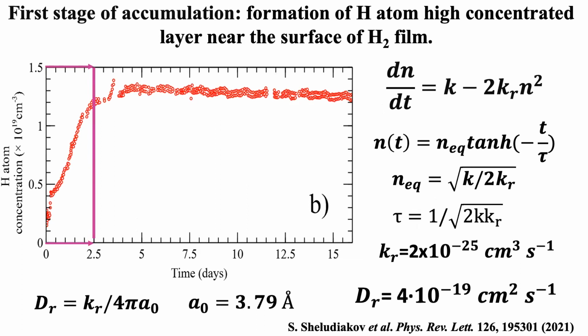So we can find this solution, and we know this equilibrium concentration from experiment. We can determine the rate of accumulation from the slope of this curve. In this case, we can calculate the rate due to recombination of the atoms, and this rate from this particular experiment was found to be this value. According to this equation, we can find the diffusion coefficient due to recombination, which is equal to around 10 to the minus 19 centimeters squared per second.